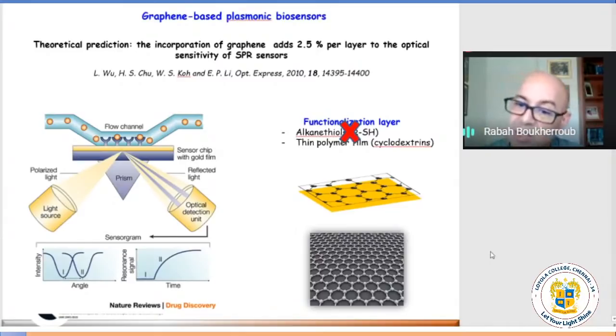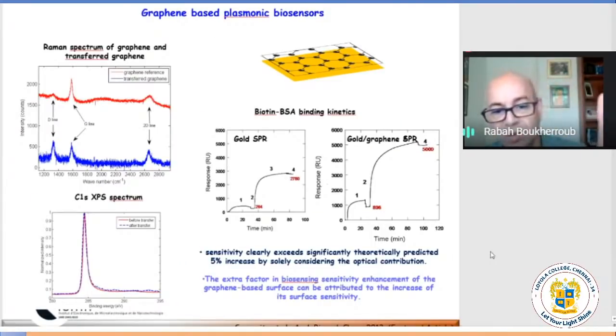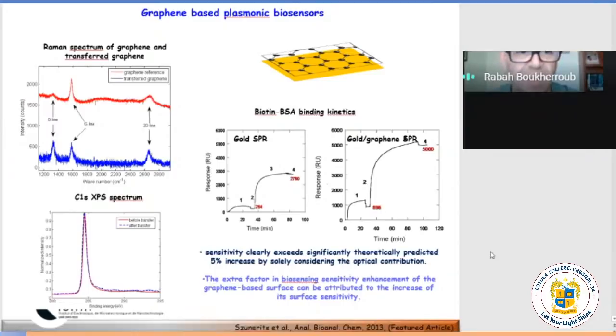So it offers really much more opportunities for making different sensors. So we had CVD graphene. You can see it here with the Raman spectrum. You have very nice graphenic lines. This is the 2D, related to the number of layers. And you see a very small D line, which is called the defect-related Raman band.